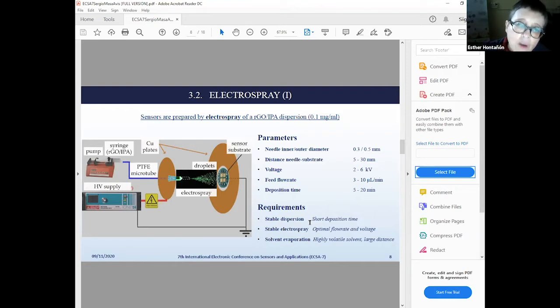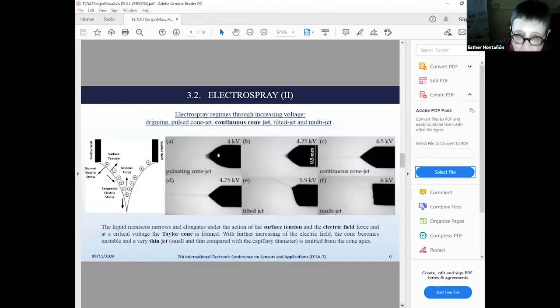And finally, the solvent must evaporate from the electrospray droplets before they reach the substrate, in such a way that only the graphene or the reduced graphene oxide flakes that are suspended or dispersed in these droplets deposit on the substrate in the absence of liquid at all, because the liquid normally leads to very inhomogeneous deposits. So we avoid deposition of liquids on the surface of the substrate.